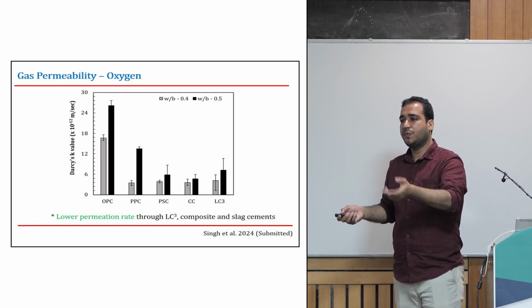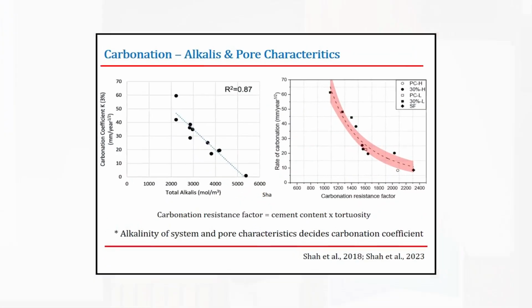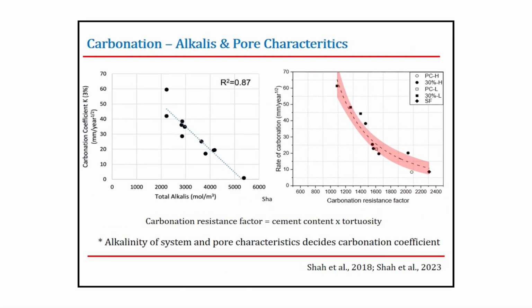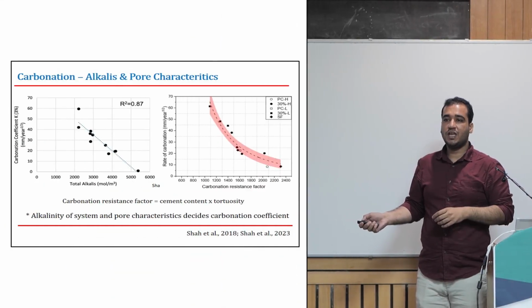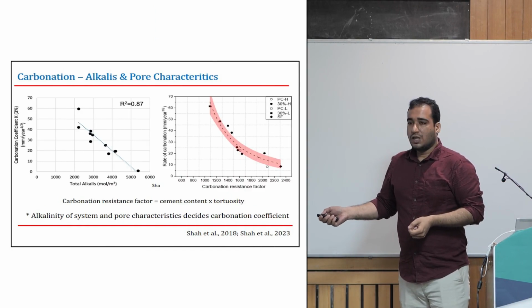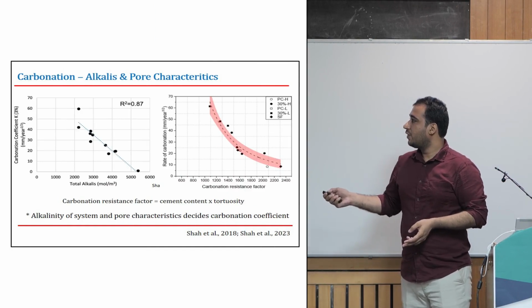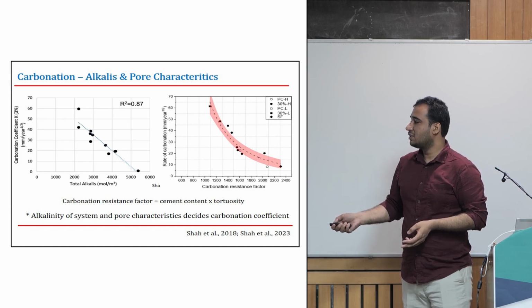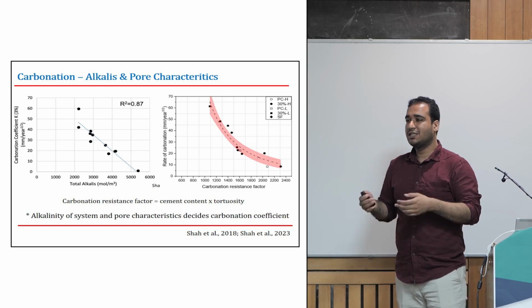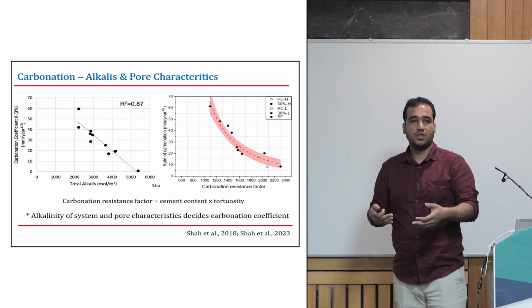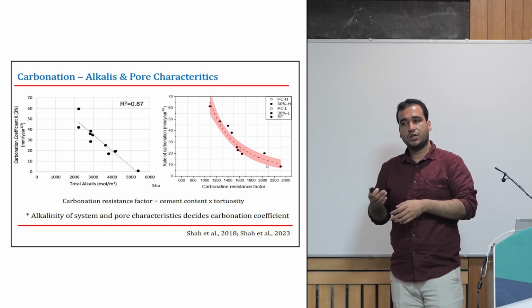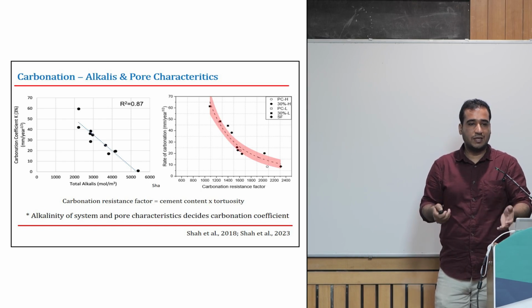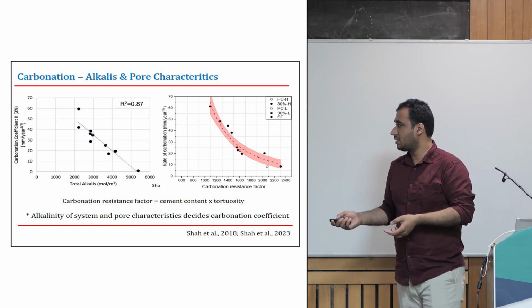But does it need to be just gas permeability that's deciding it? Probably not. It's the reserve alkalinity also. The term reserve alkalinity means the buffering capacity of the system to counter the carbon dioxide increasing in the system. In the case of blended systems, the total alkalinity is lower compared to the OPC. OPC has a quite high total alkalinity. So it's the combination of two factors. When you combine these two factors, you see a nice trend. Your alkalinity combined with the pore characteristics is what helps you assess the carbonation coefficient of your structures. Using one factor may not be a good idea. It's better to take two or three tests, combine them, and see the main result.